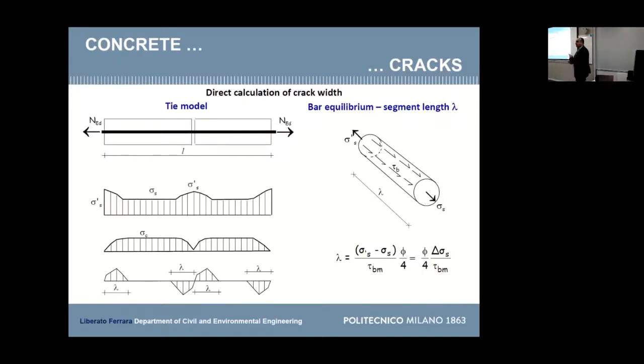We have in codes very reliable models for ordinary reinforced concrete structures. They are based on a simple tie. You apply a force to the bar, and once this force reaches the strength of the concrete at a certain cross-section, you form a crack. When you form a crack, the stress in the concrete drops to zero. It is not exactly true, because also plain concrete has some residual toughness, but we consider that it goes immediately. And the same stress is taken by the steel.